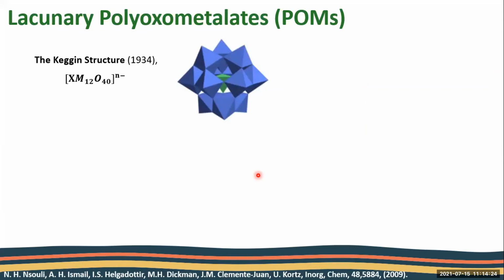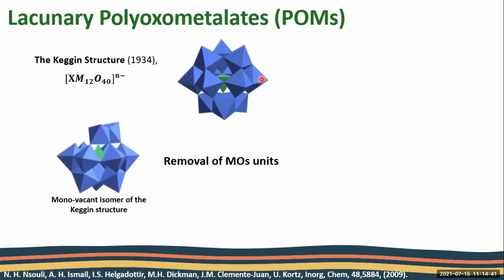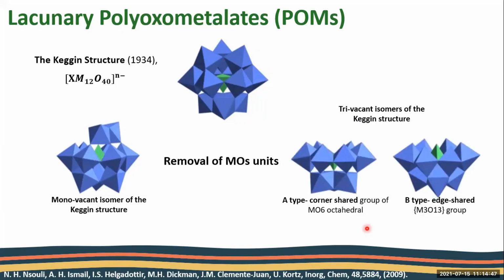Specifically in my project, we took a family of lacunary polyoxometalates, and how did we get that? This family is produced by removal of one or more metal oxo units of Keggin. So if we, for example, remove one unit, we will get the monolacunary structure. And if we remove 3 units, we will get the trilacunary structure. And in this trilacunary structure, we have 2 isomers. The first one is called A type, and that means that the units of metal oxo are corner shared. And the second isomer is the B type, and that means that the metal oxo units are edge shared.